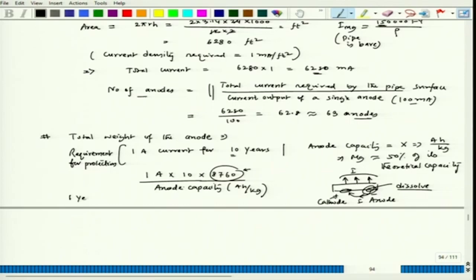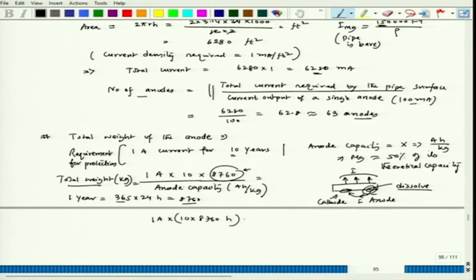So now we have to find out for 10 years how many hours it becomes. For 1 year we can calculate the hours: 365 days into 24. If we multiply, you should get this, and that becomes the total weight in kg. So 1 ampere into 10 into 8760 hour into kg per ampere hour. So this becomes this much kg. Now this is done with respect to 1 ampere, so this can vary.